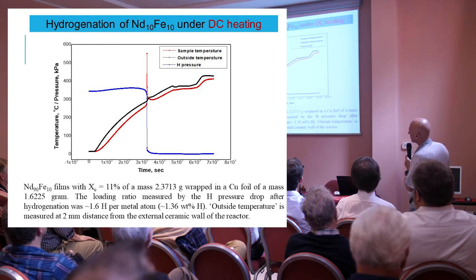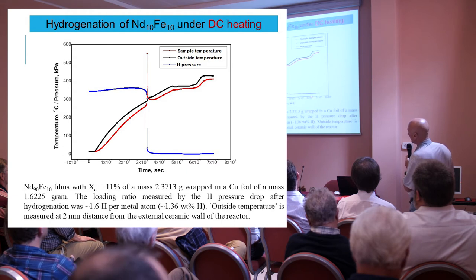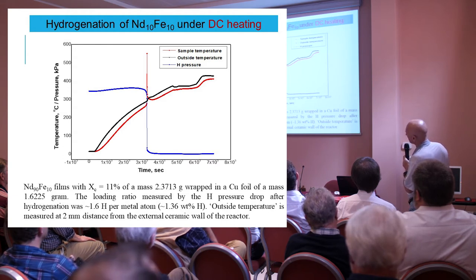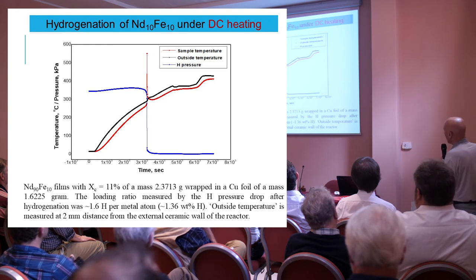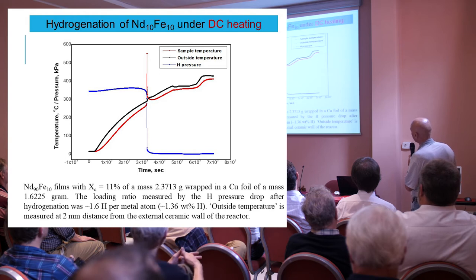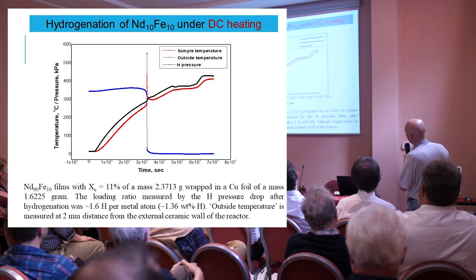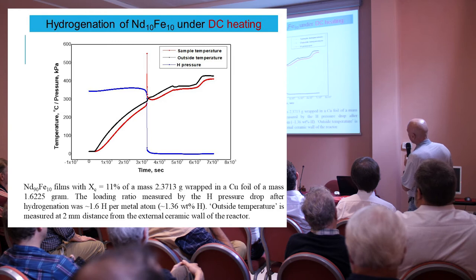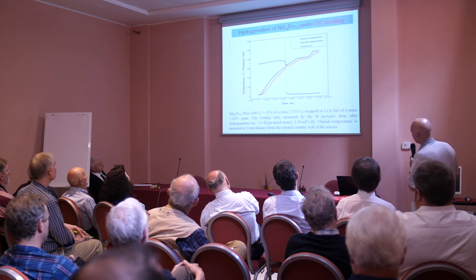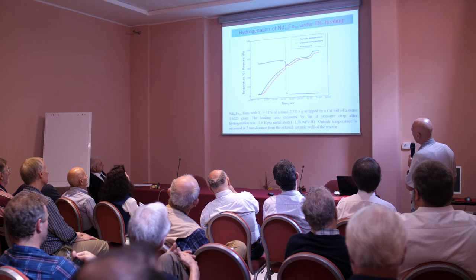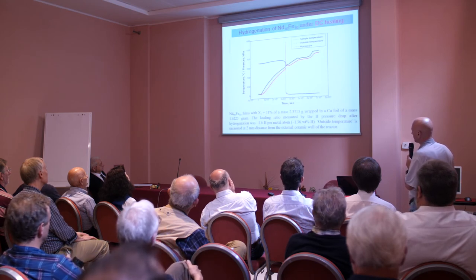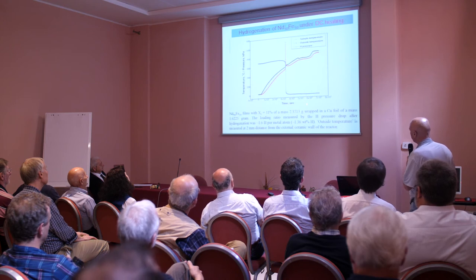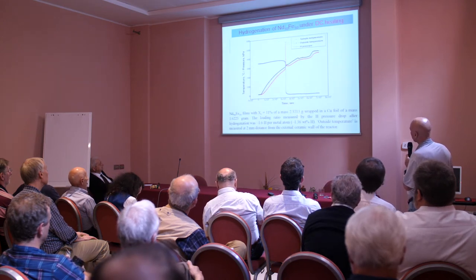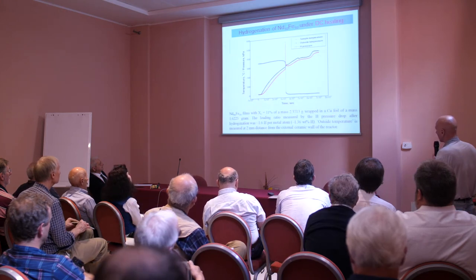Blue one is a hydrogen pressure inside the chamber. You see, we start slightly above 3 atmospheres, 3 bars. And these two are, again, the black one is a temperature outside the chamber, outside the ceramic tube. And the red one is the temperature inside the material. So this is slow heating, nothing happens, and then suddenly, very suddenly, almost all the hydrogen in the system is sucked, absorbed by the material.